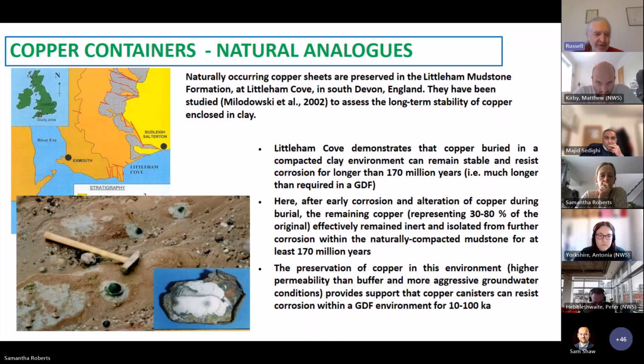Interestingly, if you compare this with the several hundred-year-old Kronan cannon, the copper here appears to have been stable and has resisted corrosion for about 170 million years. As I say, that's somewhat longer than is required in a GDF safety case. Interestingly too, the clay environment has quite aggressive groundwater and much higher permeability. So again, it provides that warm tummy feeling, if you want. Makes you think, well, that's pretty good. If these thin copper plates can survive, then a thicker copper canister should do even better.